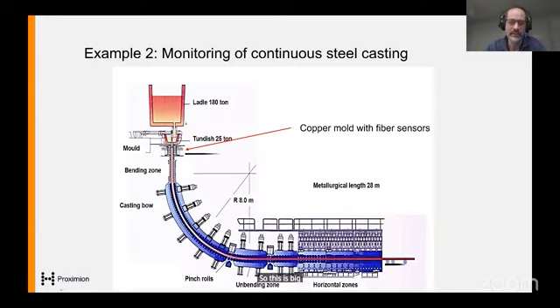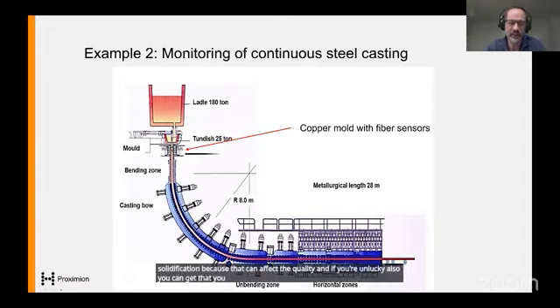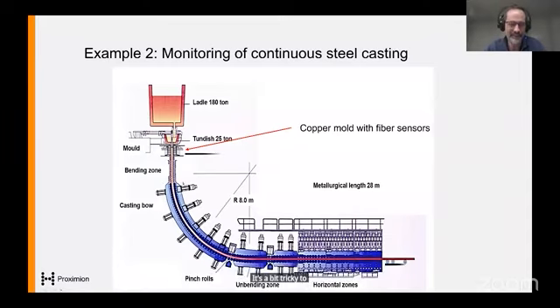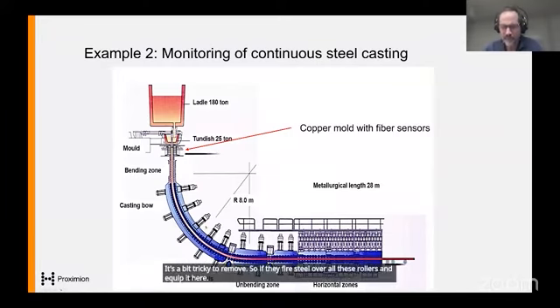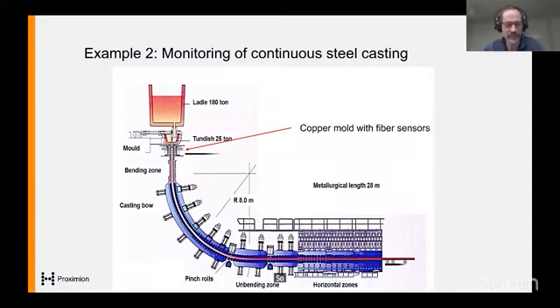But a critical stage here is the solidification, because that can affect the quality. And if you're unlucky, the surface of the steel can get stuck, and then you can get a breakout where steel flows all over, and that ends up quite expensive because it's tricky to remove solidified steel over all these rollers and equipment. So it's important to keep track of the temperature in these copper plates.